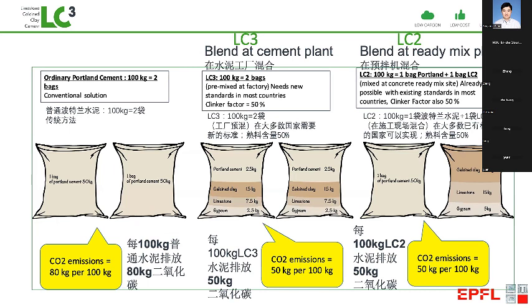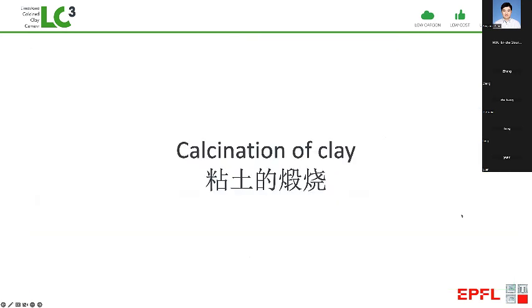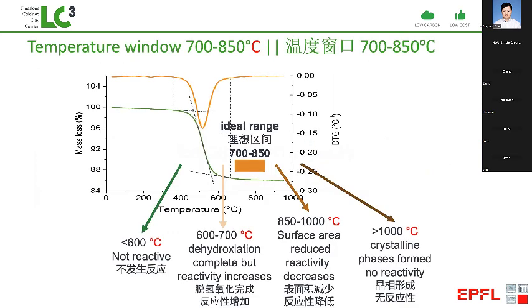And this slide just shows the same thing in another way. You either grind everything together to make LC3, or you take 1 bag of Portland cement and 1 bag of LC2 to make, again, the same composition. Now, for the calcination of the clay, what is very important is this can all be done with existing technologies. The loss of water occurs in this step between about 400 and 600, but we can really improve the reactivity by heating higher to the ideal range, 700 to 850. So this is quite a wide window, which allows easy processing.